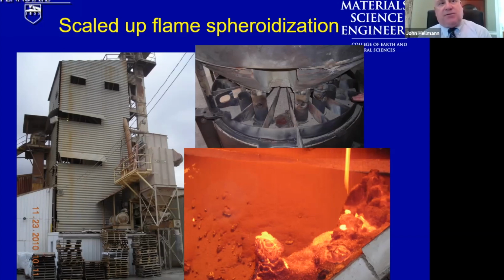The tower then consisted of 32 radially oriented gas burners, natural gas fired burners, firing at roughly 1 million BTU per hour firing rate. Those particles would melt, fuse, spheritize due to surface tension, solidify on falling down the tower, and be collected at the bottom on a vibratory bed and transported out of the furnace in such a way that we could retrieve the materials for characterization. If you look closely at this particular photograph, you'll see lots and lots of vertical striation. That is actually the falling particle rain, the incandescent particles, essentially obsidian-based glass particles falling at the base of the drop tower. So it was a pretty impressive process, and we were able to demonstrate the capability to manufacture tonnage quantities per hour in this fashion.